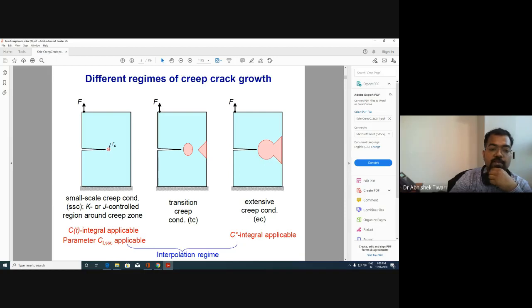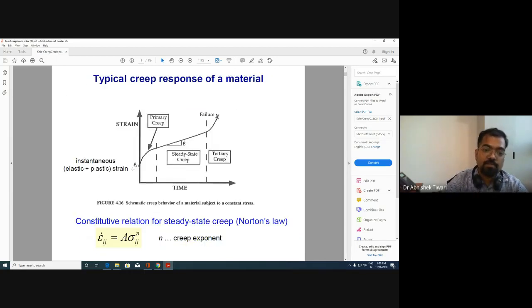This can happen also in plastic deformation, that at the crack tip, you will have a very small area initially. So once you have started applying this force on it, with time, what will happen initially? Let's go back to that strain equation. Once I apply some amount of stress, what happens initially is that some amount of strain is a response of Hooke's law, right? And then there can be some amount of strain which is plastic, due to plastic deformation, if the stress is higher than the yield strength. Now this strain which is there, which is instantaneous, with time you will get more strain because of the time dependent deformation.